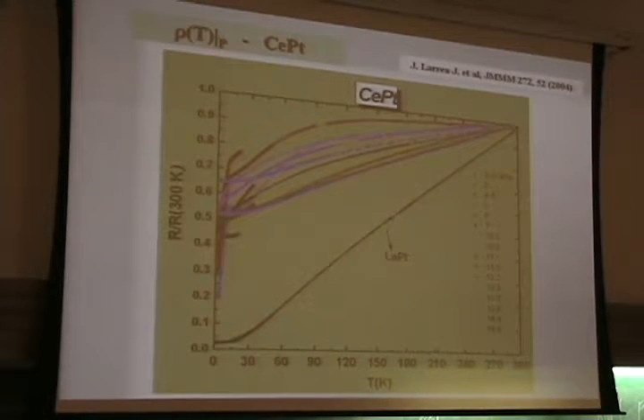Okay, and then we completed this work with the Bridgman cell, and these are some measurements. Okay, we also have lanthanum platinum to take the phonon contribution of this material. Okay, here we take the phonon contribution, but we don't make the lanthanum platinum under pressure. Okay, we only take this contribution, guessing that this system doesn't change very much with the pressure.